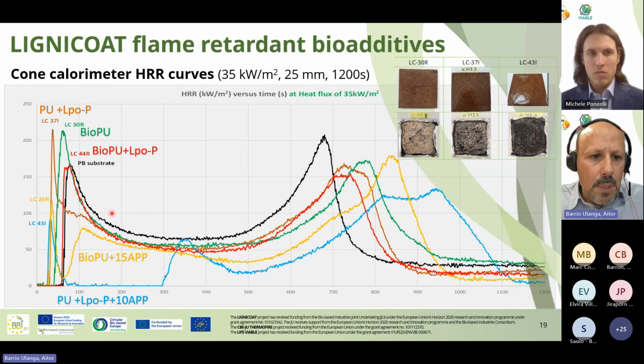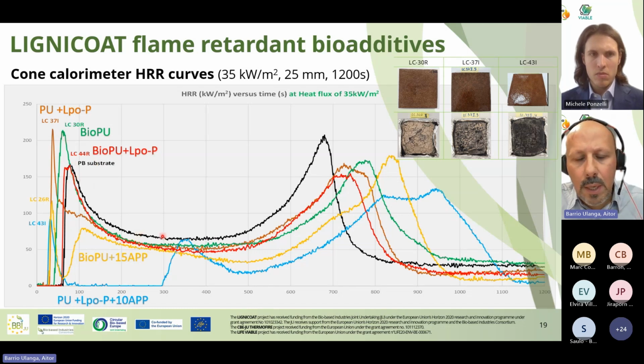You can see in black the substrate, which is a particleboard. This is the profile that starts with the ignition, releases heat, and then has a second ignition. In the case of the biopolyurethane without fire retardant, you see that the coating worsens the performance because it's ignitable and releases some heat before the decomposition of the board. And when we use as an additive just 0.3% phosphorus, we improve this performance. We are close to the particleboard substrate in reducing the total heat release, because we are under the curve of the substrate, but it's not enough.